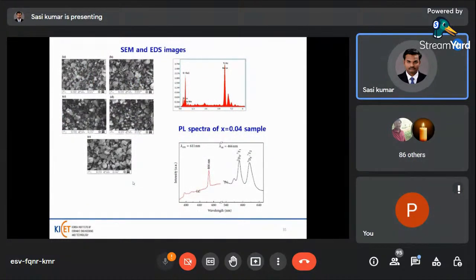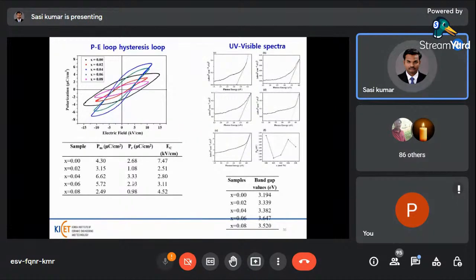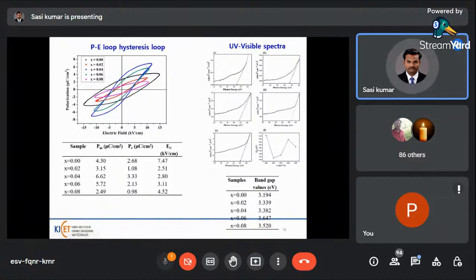And then scanning electron microscopy and the EDS spectra of these compositions, and then PL spectra of x equal to 0.04 composition are also shown here. The emission wavelength is 611, consistent with the previous report. And then the PE hysteresis loop, here the highest value of polarization is observed in the 0.04 composition, and then the UV spectra give the band gap values of the Nd doped barium titanate, also mentioned here.